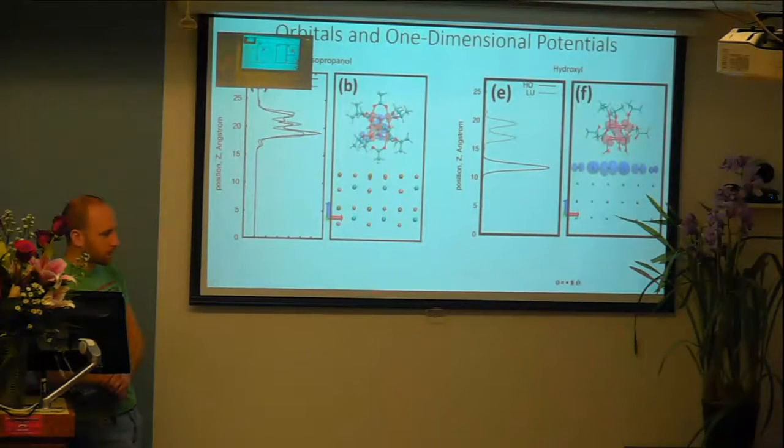And then your titanium dioxide would be the sensitizer in this case. And then you need a charge transfer from the titanium dioxide to either both occupied states or both unoccupied states. I mean, after you optimize it, of course, you create a hole, and then the hole goes. Then hole transfer means an electron from one material goes to the hole state of the other material. But not that you're exciting this charge transfer state, because such a charge transfer state would be optically inactive.